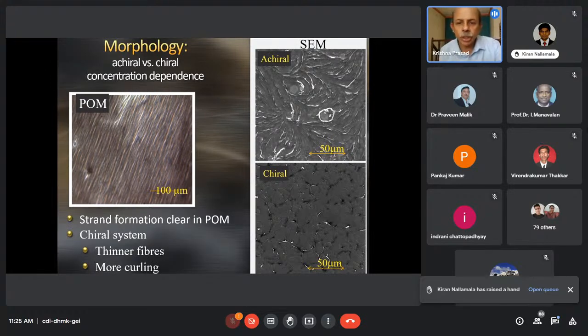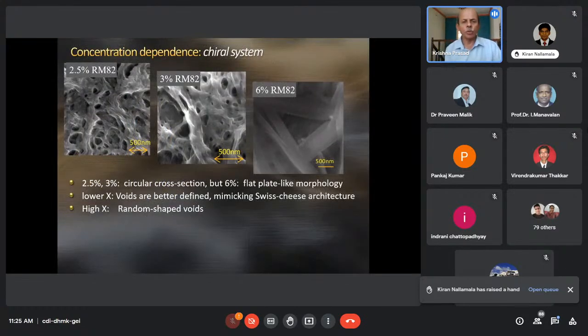So the achiral systems, the fibers are striped fibers, whereas in the chiral ones, where you have a chiral component which transfers the chirality of the liquid crystal onto the fibers, you have a significantly curled up kind of polymer architecture. And so this chiral influence is what we talked about in detail when we were talking about these systems, wherein the chiral transfer takes place from the liquid crystal to the polymer architecture. As you change the concentration, the amount of chirality transfer changes in a non-monotonic fashion. Up to a certain concentration, the system tolerates the transfer, and therefore you have more and more curling up as you increase the concentration of the polymer. But beyond a certain concentration, you lose the chirality transfer and they go back to striped fibers.